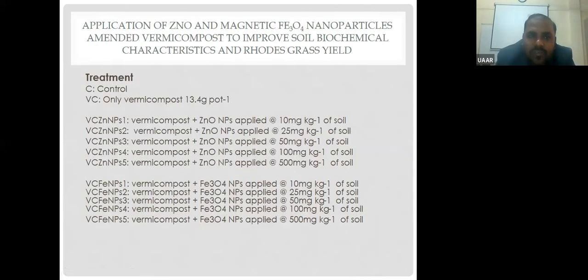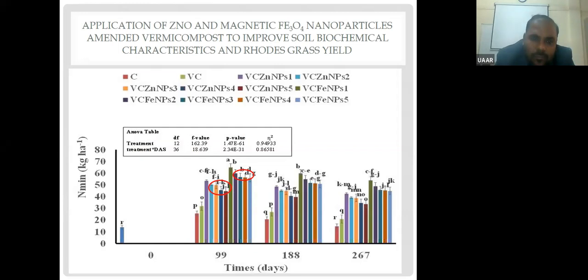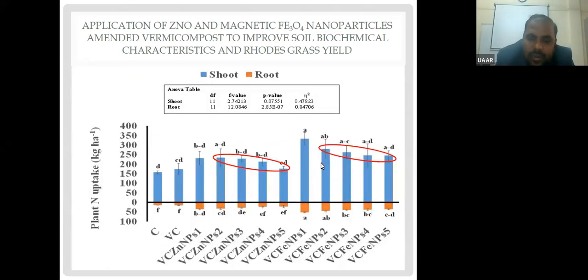Next, the toxicity of zinc oxide and iron nanoparticles amended vermicompost to improve soil biochemical characteristics and Rhodes grass yield. Again, there is a toxicity at high doses. So different doses of these nanoparticles, zinc and iron oxide, were used, starting from very low 10 to very high doses, from 10, 25, 50, 100, and 500. If you look here, then an increase in the doses decreases the N mineralization. Only the 10 is a little bit acceptable. And if you look at 25, 50, 100, and 500, then the N uptake has been significantly going down.